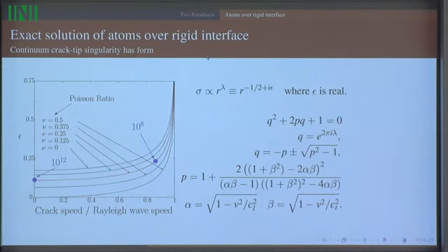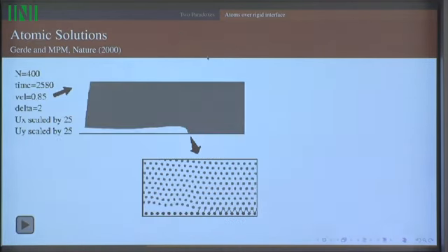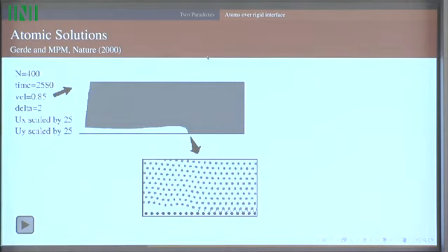I'll remind you again that I claim that fracture is a problem where unless the system can resolve paradoxes down at the atomic scale below the scale at which you're worried about continuum theory, the solutions may not exist at all, like the fact that brittle fracture really does intrinsically jump from low to very high speeds. I would say that the fundamental reason for that is that the atoms just can't figure out what to do. So if the atoms can't figure out what to do here, you wouldn't get solutions. If the atoms can figure out what to do, then continuum theory kicks in and you can just use it. So I'll provide you just a little movie of what some of the solutions look like,